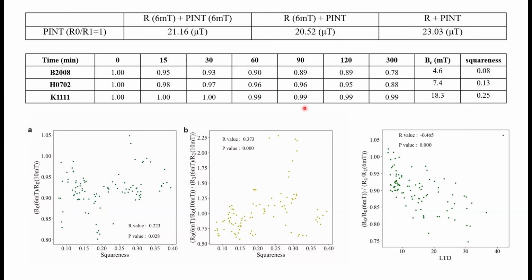And we tested this effect, and the sample here is more MD, and the sample here is more SD. And we can see for the MD samples, it will lose its remanence about 10%, but for the SD samples, it will keep stable.